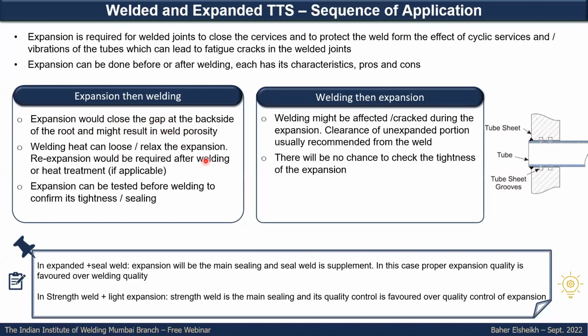So you might have a higher chance of weld porosity, especially in the root pass of the weld. Also, when welding after the expansion, the heat from the weld, and maybe from the post-weld heat treatment if it is required, will cause some loosening of the expansion. So whatever expansion you have done earlier will not remain intact after applying the welding.